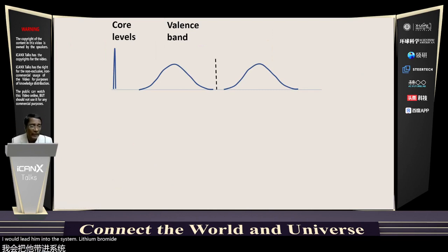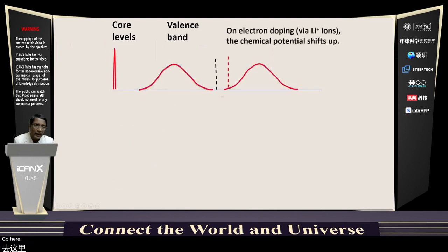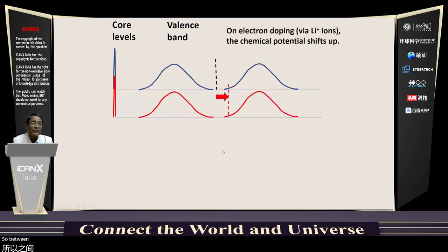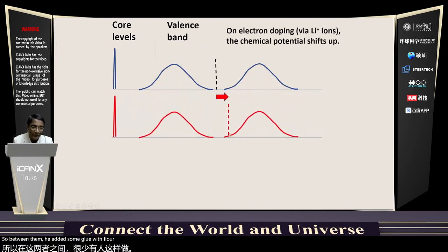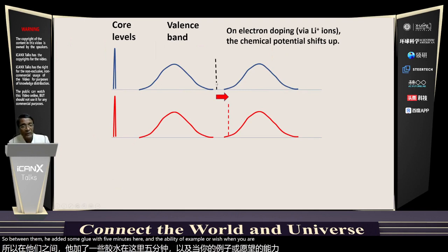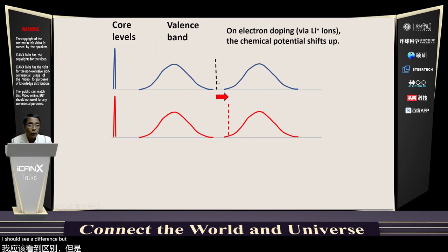Lithium dopes electrons. Where will those electrons go? The electrons will go here. That means my Fermi energy will move up. So between the lithiated sample with Fermi energy here and the unlithiated sample or well-washed sample, the Fermi energy here, I should see a difference. But I don't see the Fermi energy difference because photoemission always aligns the Fermi energy.